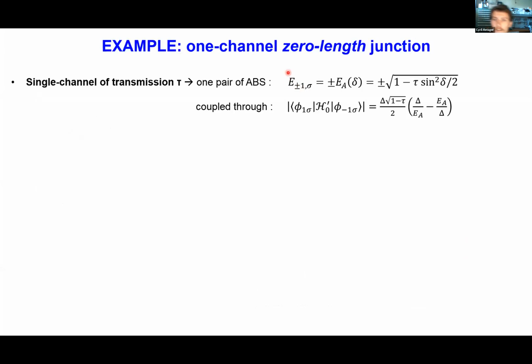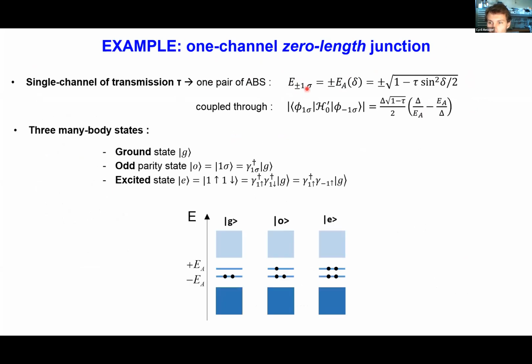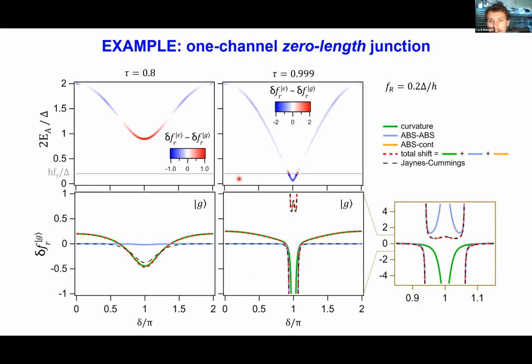So let's illustrate this with the simple case of a one-channel zero-length junction. In this case, everything is very simple because we have analytical expressions, both for the energy of the two Andreev bound states, for the matrix element of the current operator that is coupling them, and so we also have an analytical expression for the shift. Now, because we have only two Andreev bound states, there are only 3 states that you can build. So the ground state that I already presented, and then the odd parity state where you would add 1 quasi-particle, and the excited state which corresponds to 2 excitations. So in the interest of time, I'm not going to give you the details of the computation of the shift, but just show you the theory on 2 illustrated cases.